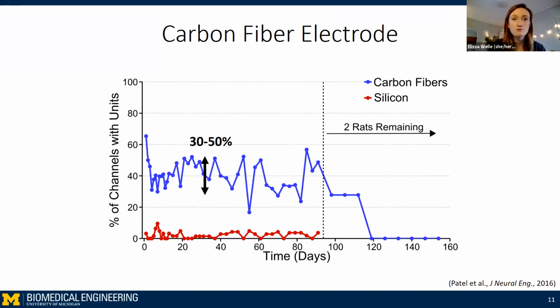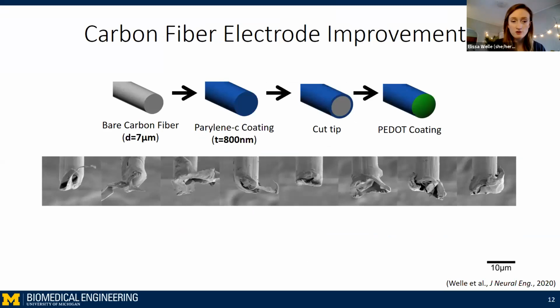And we took a look at our fabrication methods. There's more about this in our papers, but briefly here, you take a bare carbon fiber, we coat it with parylene C, as I mentioned before. We then cut the tip using microsurgical scissors, and then we electrochemically deposit PEDOT:PSS on the exposed carbon. And when we took a look at these traditional scissor cut electrodes under SEM, however, the results were not great. We saw that the carbon was really inconsistently exposed from parylene. The sites were rough. It was overall highly variable. And we felt like this was a first and necessary step to improve upon.